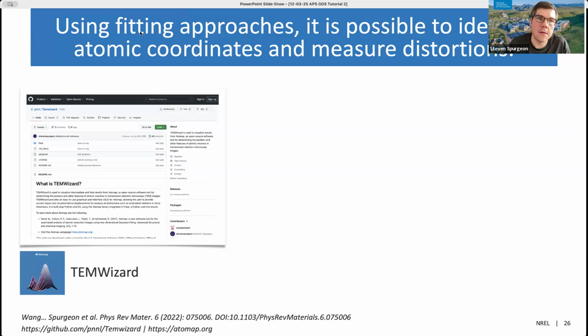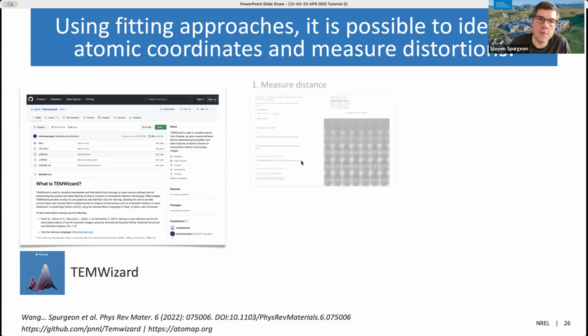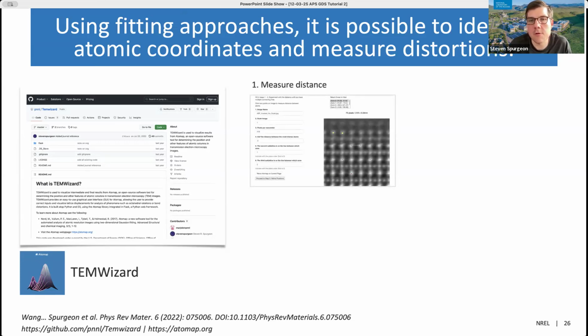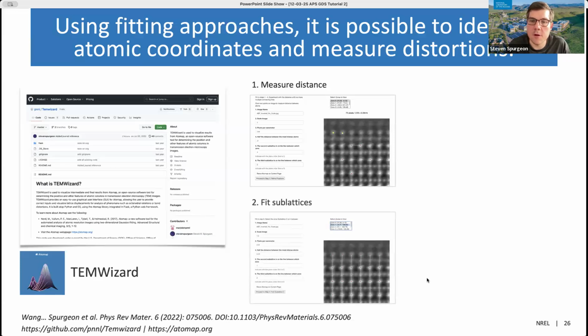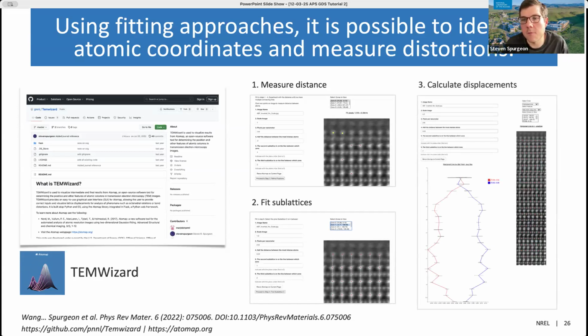Using the statistical approaches and fitting approaches that I talked about, we can really improve the process of understanding atomic coordinates and measuring these types of distortions. The approach works by using essentially 2D Gaussian fitting to provide an initial guess for the atomic positions through manual selection or measuring some basis vectors within the crystal. We can then refine atomic positions. We measure distances and define sublattices through the 2D Gaussian fitting. We then have a map of the coordinates of the atoms within a given sublattice. Then we can calculate in a statistical way what the displacements look like, not just in a single column of atoms, not just in one line profile, but actually on an atom by atom basis.